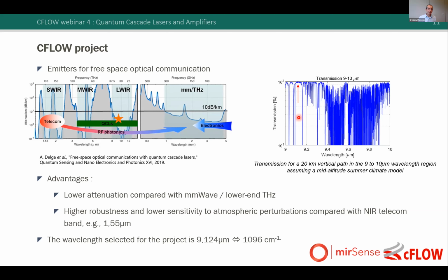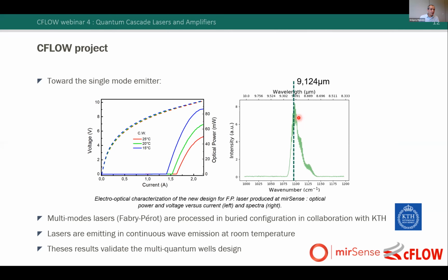So the aim of mirSense in the project was first to develop these single mode emitters for the free space optical communication. The first step in the development of this realization was to validate our design of the multi-quantum well structure used to generate the photon. To do so, we have processed this structure using a Fabry-Perot configuration. And thanks to the collaboration with KTH, we used the iron-doped indium phosphide regrowth to perform a buried configuration on these lasers. And we have achieved a continuous wave emission at room temperature.